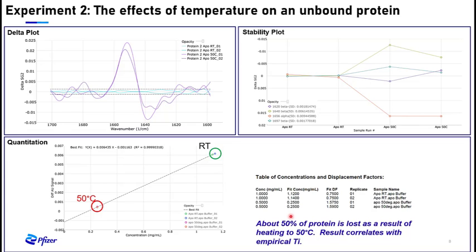Well, if you remember, our TI for this protein was about 47 degrees, at which half of the protein has unfolded. Lo and behold, it shows that here we've lost just that, 50% of our protein. A nice correlation with our calculated TI.